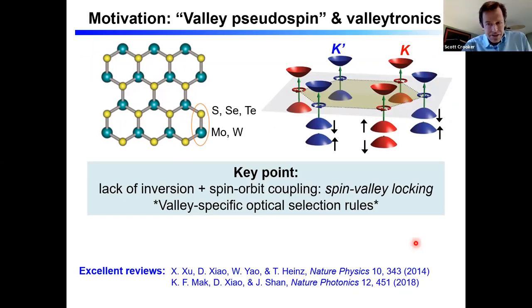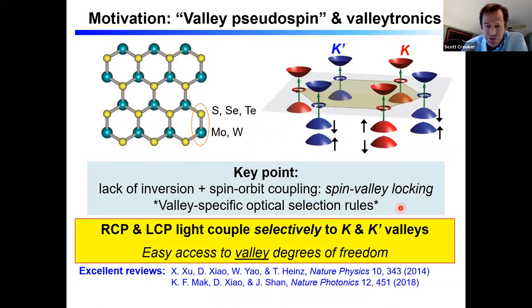Now, at least for physicists, one of the main motivations for studying these materials is that they've really revitalized and rejuvenated some very old, long-standing interests in so-called valley pseudospin degrees of freedom. And what does that mean? The key point here is that because these materials lack a center of inversion, and because of the large spin orbit coupling afforded by these heavy atoms, we get this phenomenon known as spin valley locking. What that means is that the valence bands in particular at the K and the K prime points, that's the red and the blue, have the following order. In the K valley, the highest valence band is spin up. In the K prime valley, the highest valence band is spin down. And there's a huge splitting between these, hundreds of millivolts. What this leads to is something known as valley specific optical selection rules. And the main message here is that right and left circularly polarized light couples selectively to optical transitions in K and K prime.